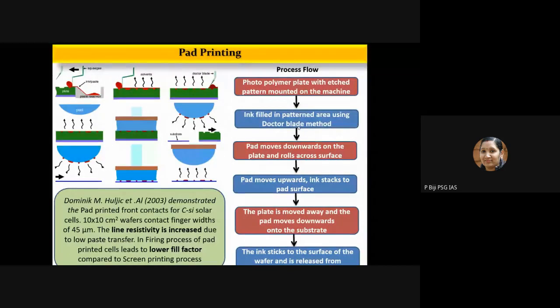Then the plate is moved away from the pad and the pad moves downwards onto the substrate. At that time, the ink sticks onto the surface of the wafer and is released from the pad as the pad lifts upwards. So that's the main process flow which is adopted in pad printing.